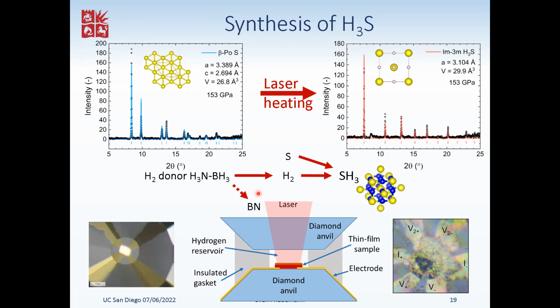We want to reach temperatures that are both sufficient to dissociate the ammonia borane, as well as to provide the energy to induce the chemical reaction to form H3S. You might ask what temperatures are required. That's purely empirical. There are no calculations, including ab initio calculations, that tell you what barriers are there between different phases. So we usually heat samples to about 1500 to 1800 Celsius for half a second, and maybe repeat that a couple of times to induce the reaction.